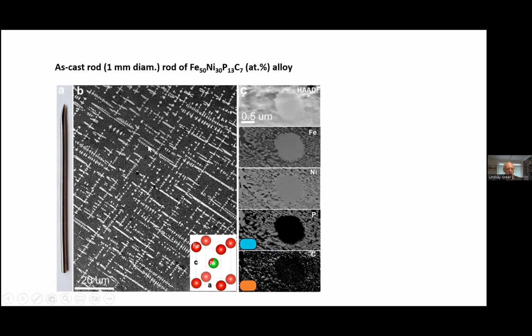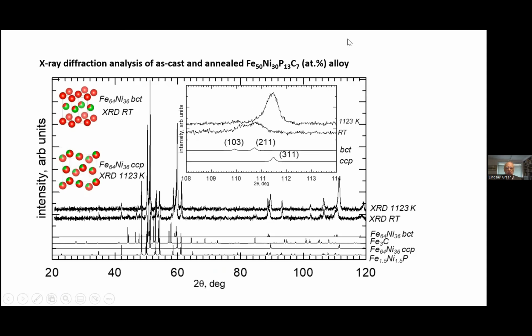These dendrites, as they're known, are the growth pattern inside the alloy, and they are crystals, and we did not expect to find anything interesting. We expected, based on iron-nickel, that the structure in these dendritic forms would be simple face-centered cubic. But on analysis in the X-ray pattern, you look at peaks to determine the phase. For face-centered cubic, you should just have a single peak in this region of the diagram, and we saw a sign of splitting. And that would be characteristic of tetrataenite.